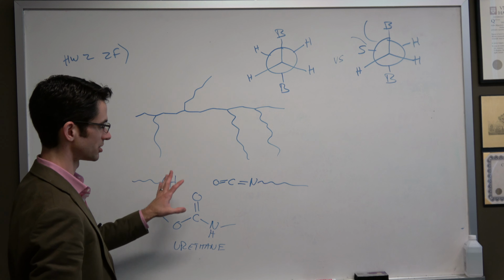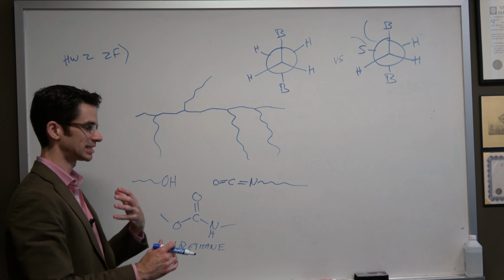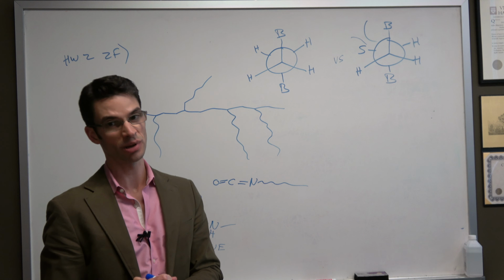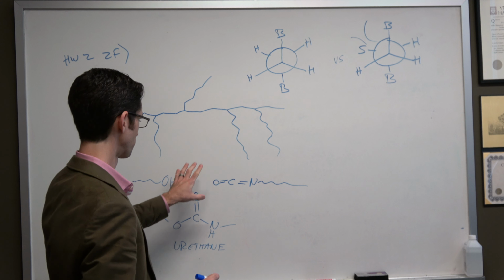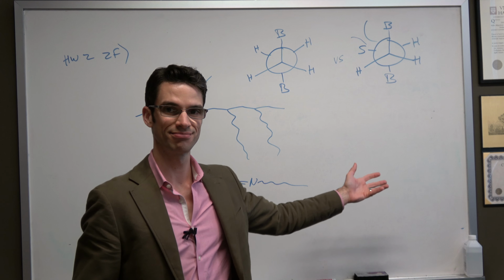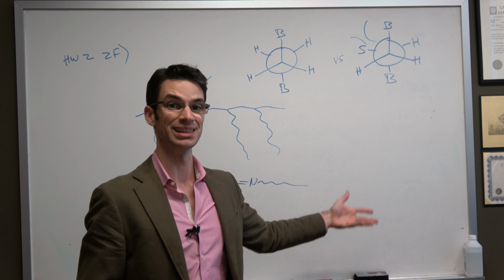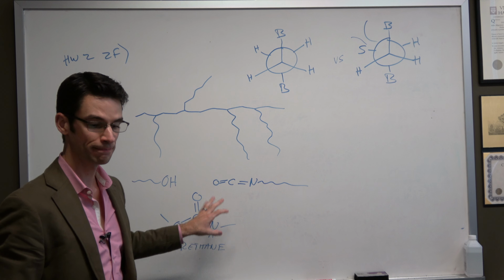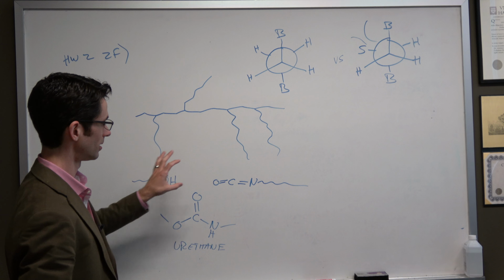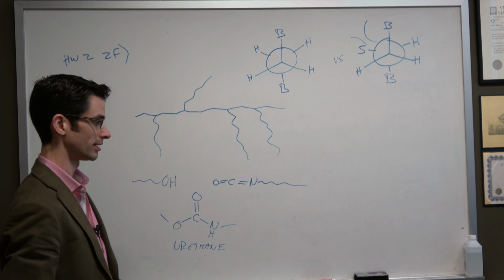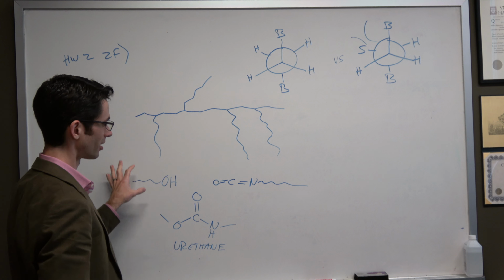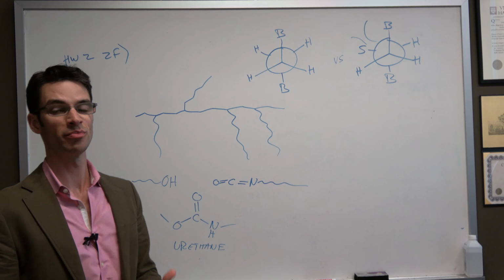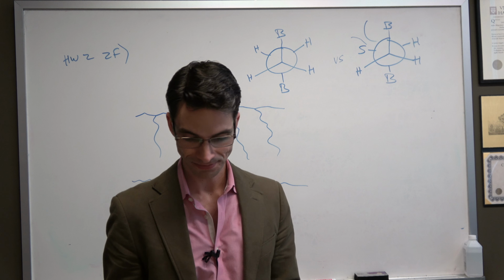The reason why this is interesting is because it follows step growth polycondensation-like kinetics, but strictly speaking, it's not a polycondensation because there's no small molecule that's condensed that leaves the reaction. All the atoms here are accounted for in here. So alcohol plus isocyanate gives you a urethane. So a diol plus a diisocyanate gives you a polyurethane in an AA-BB type polymerization.